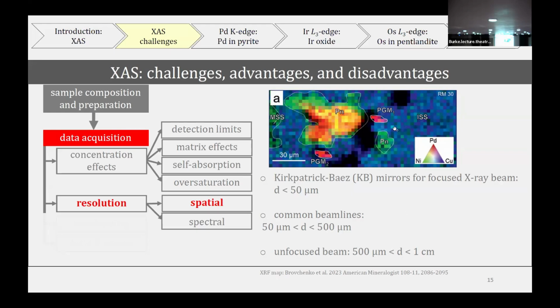I find this is an amazing example from Lera Brovchenko's paper, and you can see here that they used quite a submicron size beam, and for a reason, because this is a palladium-bearing pentlandite, and around there are platinum group minerals. If they would choose a big beam size, they would have a contamination of the signal, and it would be very hard to process the data.